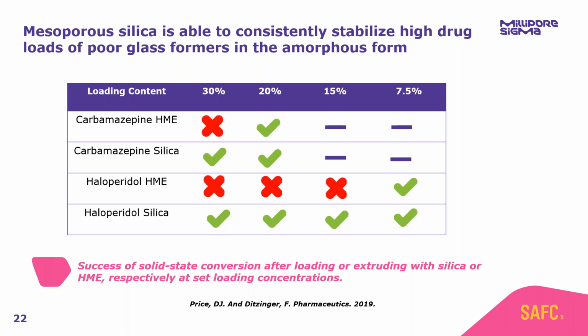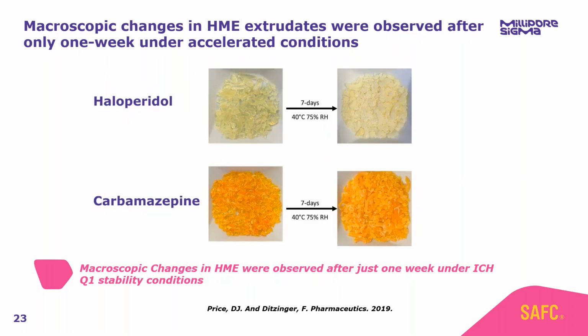But the comparison didn't stop there. We then stored these successful formulations under the accelerated conditions. So we took the 7.5% samples for haloperidol and the 20% samples for carbamazepine, and we stored them at 40 degrees Celsius and 75% relative humidity. Straight away, we could see macroscopic changes in our HME extrudates after only 1 week.